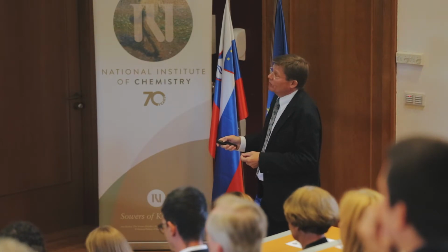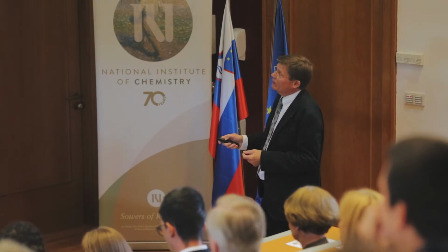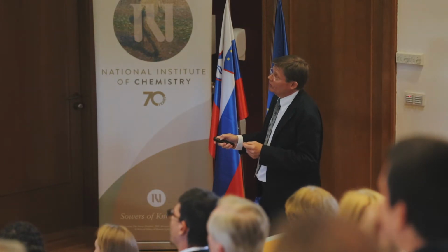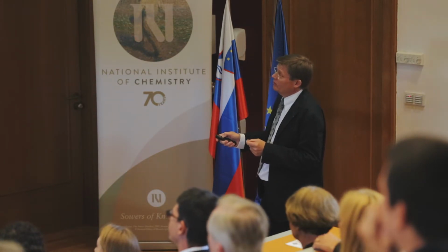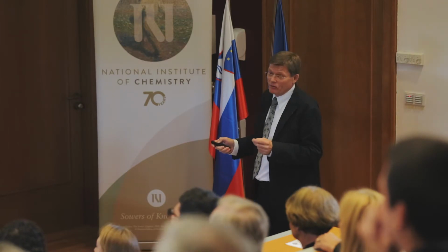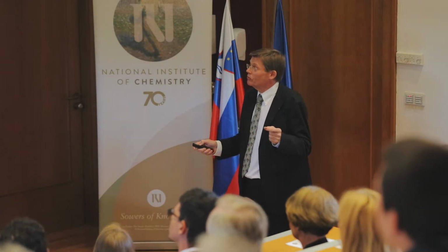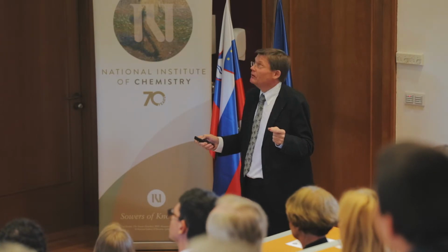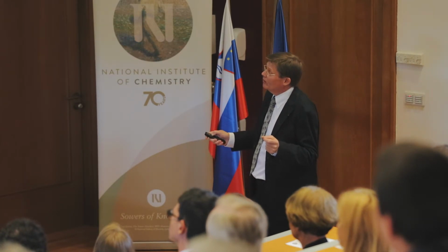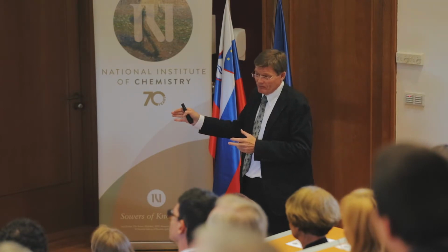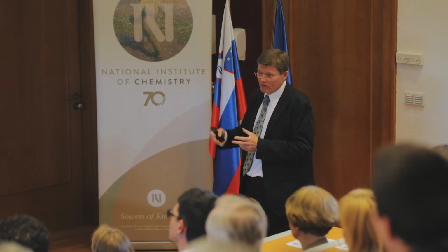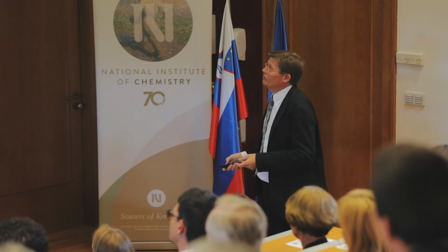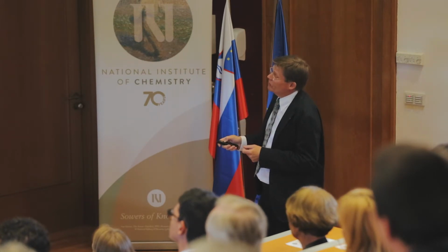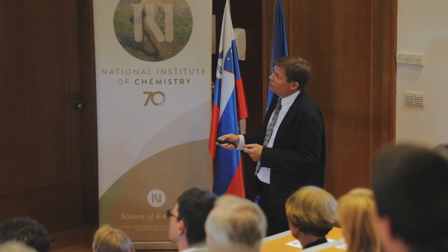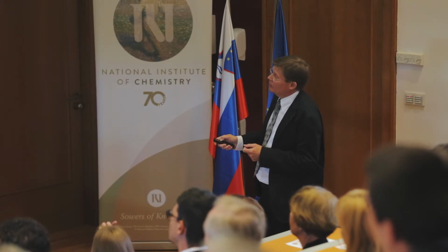He described the situation thermodynamically very nicely, and in most cases the voltage is given by this simple expression. There is one term which looks like a normal electrostatic capacitor, voltage proportional to charge. But then you have another one that looks more like what you expect from chemistry. It's a logarithmic variation, and that's actually the configuration effect. So when you now express it in terms of lithium activity, which is the exponential of this, you have a power law, and you have this exponential.